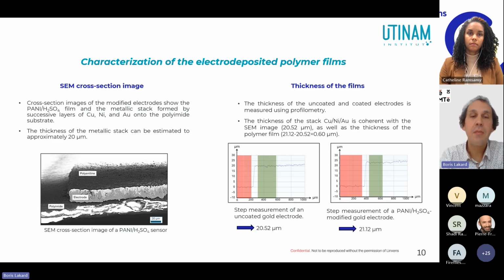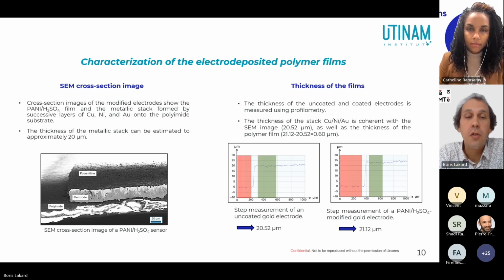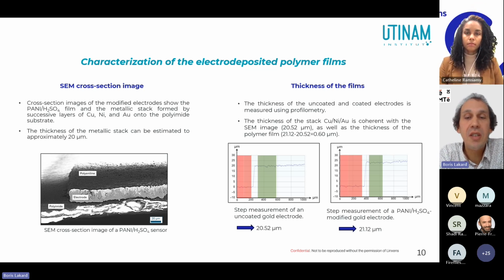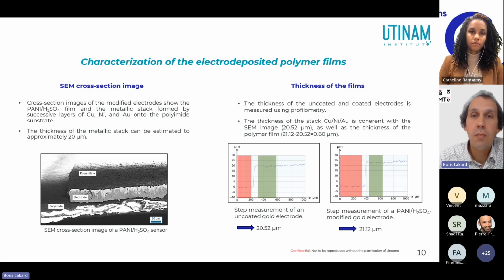The thickness of the film was then measured by profilometry. You can see some of the profilometric measurements on the slide on the right. Before electrodeposition, the thickness of the electrode was 20.5 micrometers. After electrodeposition, the thickness was 21.1 micrometers. The thickness of the polymer film was therefore approximately 0.6 micrometer.